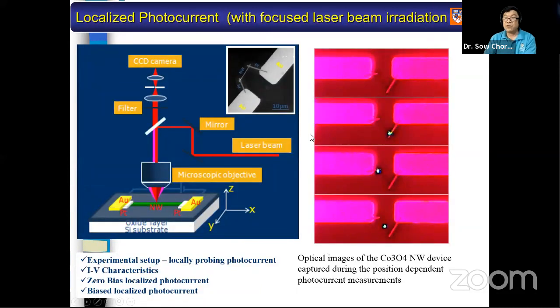So we use a focused laser beam now. You see the picture, electrode, and there is a nanowire that is in contact with the electrode. We can choose to illuminate our laser light onto the junction or onto the nanowire itself. In this case, the response that you measure will come primarily from, whether the response comes from the contact or comes from the nanowire itself. So is it intrinsic behavior or due to the junction formation?